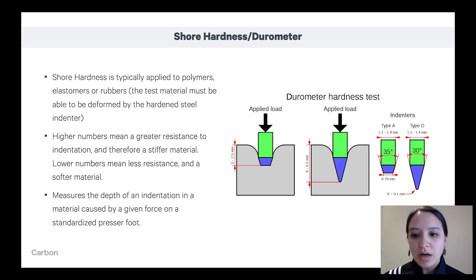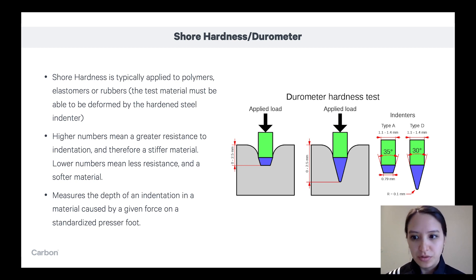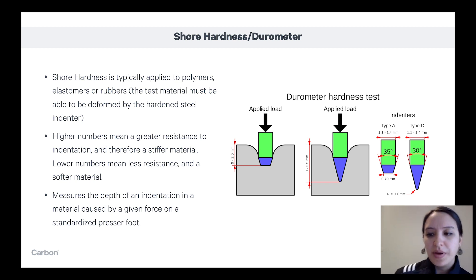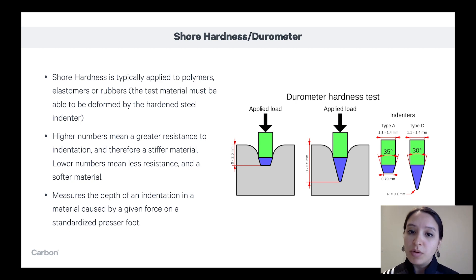Let's move on to shore hardness, another specification you see for a lot of 3D printing materials. Shore hardness, or durometer, is also measuring hardness but in a different way. It applies a given force to a very specified presser foot or indenter, and the depth of that indentation is read out as its durometer. As you can see in this figure, there are generally a lot of different types of presser feet, but the two most commonly used are type A and type D.